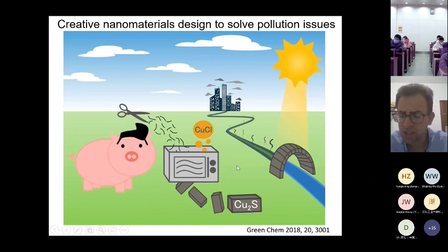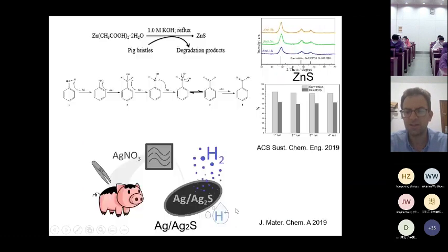And the beauty of this protocol is that, switching from metals, we can design other types of materials: zinc sulfide, molybdenum sulfide, silver sulfide, for other types of applications. So silver sulfide for selective oxidations that you see in there, for the selective conversion of toluene to benzaldehyde with a minimum production of benzoic acid. Again, using the same concept, zinc precursor, pig bristles to zinc sulfide.